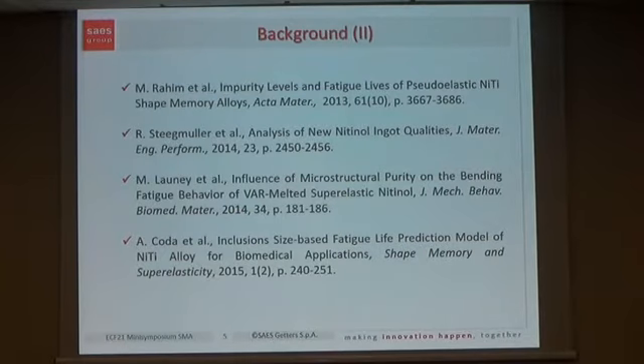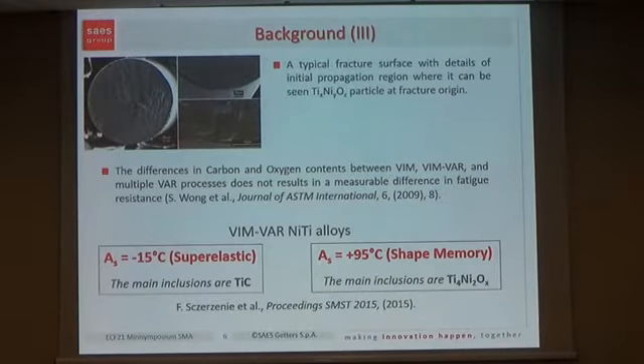But quite recently, several works, systematic studies, were done by different groups, and they at the end came to the conclusions that the inclusion size has effects on the fatigue behavior, and it is one of the most important effects of inclusions. Some statements before presenting our work are necessary. In our experimentations, and this is the first part of the story, we try to understand if there are some effects and what kind of effect the inclusions have.